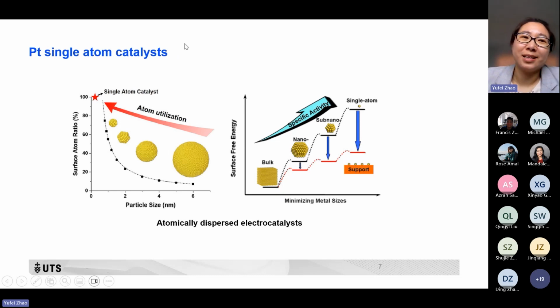So we start from the single atom catalyst. The single atom catalyst has been quite a hot topic in recent years. When we decrease the size of the metal nanoparticles, from large size to smaller size and then to single atom catalyst, we see the exposed surface atom ratio increases very fast. The metal atom utilization also increases very fast correspondingly. When we reduce the size of the metal nanoparticles to the single atom catalyst, we can assume the metal utilization can reach almost 100%. That means all the metal deposited on the substrate can be utilized as active sites for the electrocatalytic process.